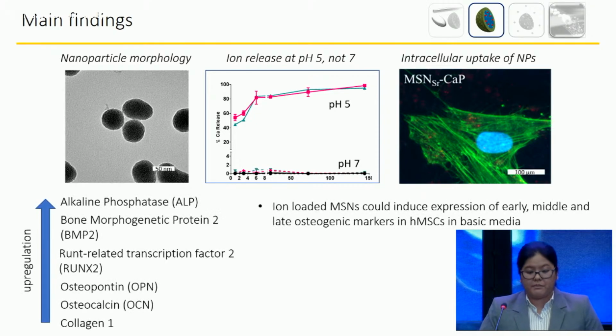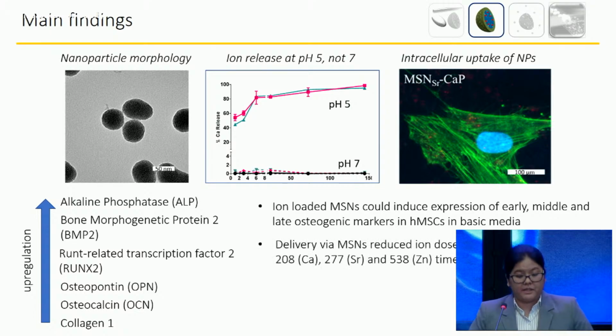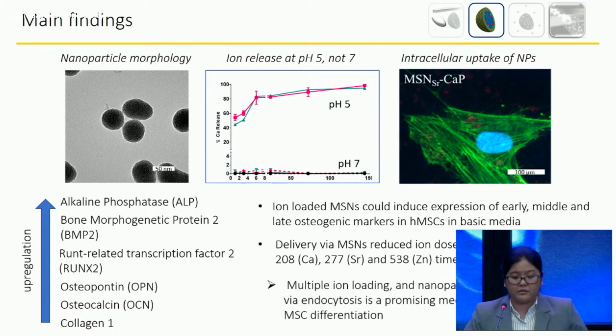The ion-loaded MSN could also induce the expression of early, middle, and late osteogenesis markers in HMSC in the basic medium without other stimulants. Delivery by MSN reduces the ion load needed to stimulate osteogenic activity in the stem cell, much less than the direct ion addition in the medium. Multiple ion MSN was also found to be more efficient in stimulating osteogenesis than the single ion. Therefore, multiple ions and nanoparticle-mediated uptake via endocytosis is a promising mechanism to promote HMSC differentiation.